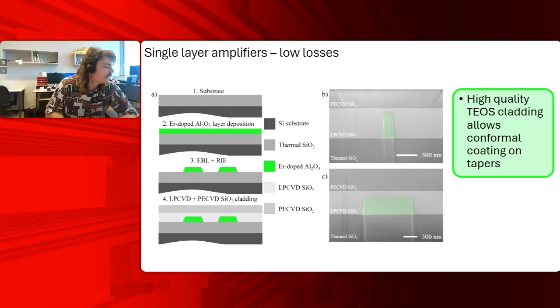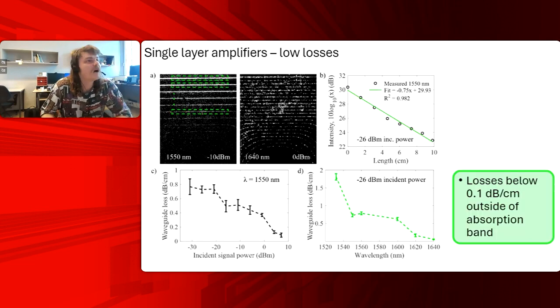Just a quick recap that this TEOS cladding, so an LPCVD that relies on, I won't go through the whole formulation of the chemical for TEOS, but it can allow very, very conformal coating for the tapers, and then these nano sections on the top, SEM that you can see here, to allow low coupling losses. These low coupling losses are also accompanied by low propagation losses. Using simple image analysis, we can extrapolate 1550 in the absorption band and 1640 outside of the absorption band for losses for an amplifier. This is all now for doped devices, where we recently measured background propagation losses below 0.1 dB per centimeter at 1640 outside of the absorption band, which you see there in inset D for very, very low signal powers. That's exciting.